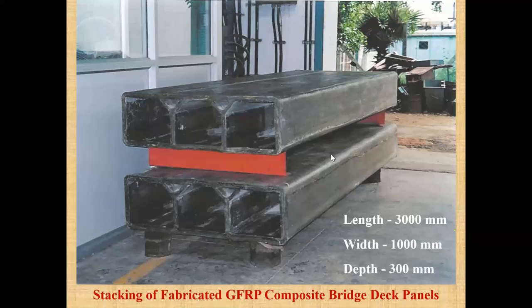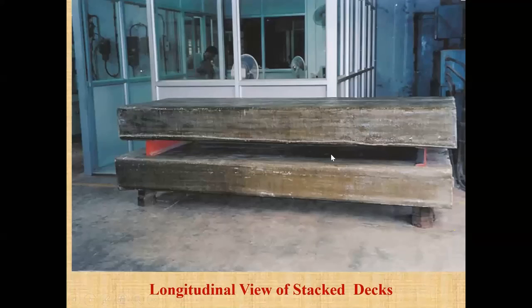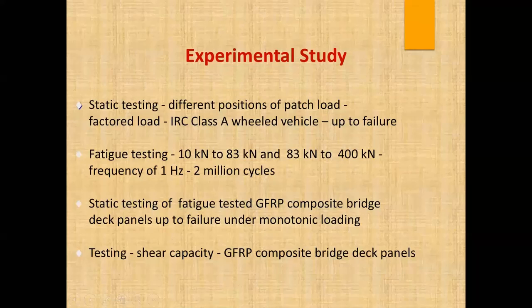So this is another longitudinal view of the deck. The experimental study was static testing, with different positions of patch load applied, and IRC class A wheeled vehicle up to failure. Fatigue testing was around 10 kilonewton to 83 kilonewton and 83 kilonewton to 400 kilonewton, at a frequency of 1 hertz, 2 million cycles. Then static testing of fatigue tested GFRP composite bridge deck panels up to failure under monotonic loading.